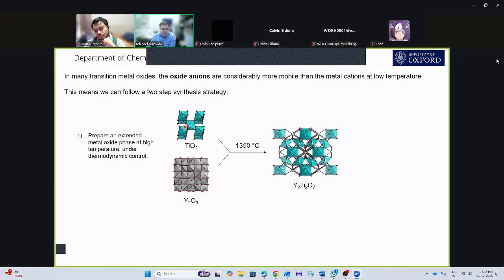So in this example, I can take titanium oxide and yttria and grind them together and then heat them at a really high temperature to make this phase here, Y2Ti2O7, which has the pyrochlore structure. So this is just a thermodynamically stable material. But it's what I do next that's interesting.